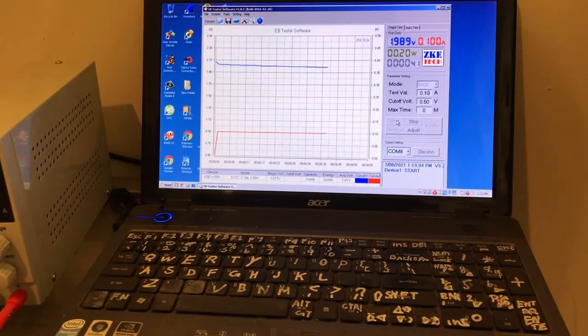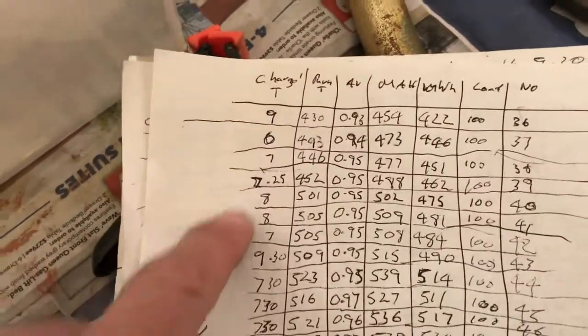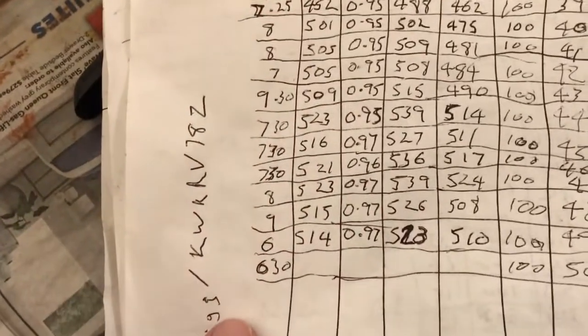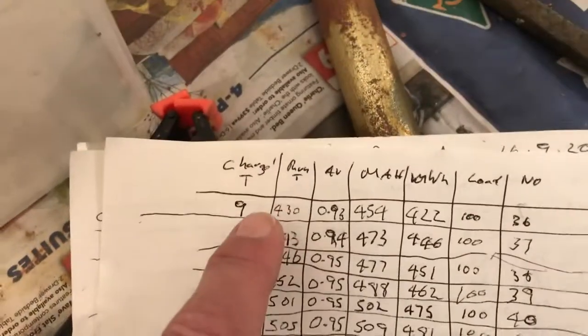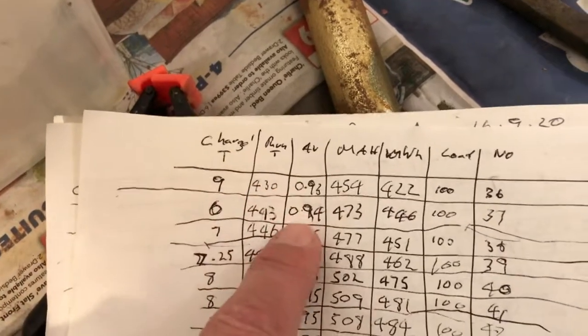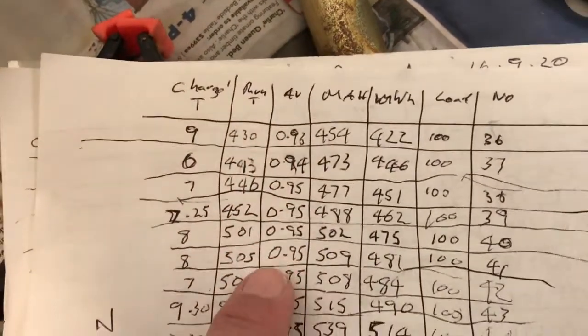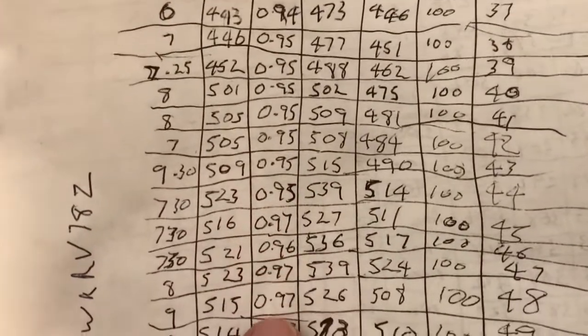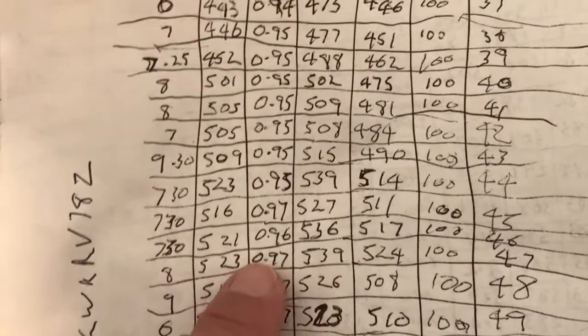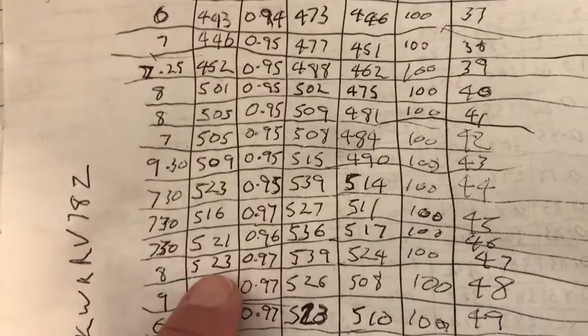Just had to turn the coffee off. So it's at 1.9 for a minute. It drops down rapidly to about 1.2 and then it holds for a while. So what's happened over the 50 charges? I have various runtimes for charges. The real noticeable difference is the average voltage has started to increase over time, and we're now at a level of 0.9 for our 5-hour run.